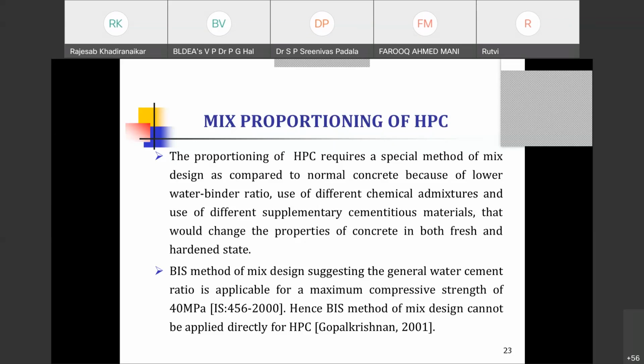Then the chemical admixtures are also equally important. They must have a longer chain length, and you must consider durability issues and mainly all the compatibility issues. You have to work out the dosages, the chemical composition, and all those things, and have a clear idea before using them. Otherwise, there will be a lot of issues. Slump loss problem will be there, and segregation problem is also there. Like that, so many issues are there. The higher the solid content, the better the effectiveness will be. Longer chain length is also better. Like that, those basic issues are there.